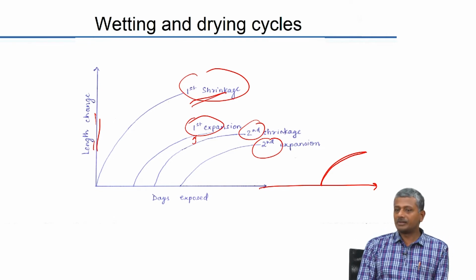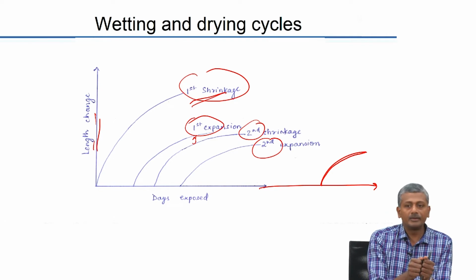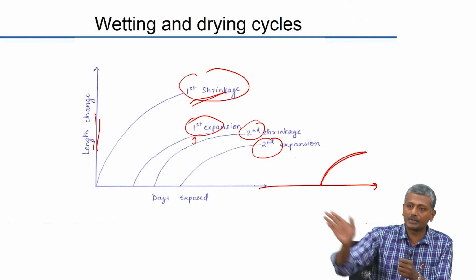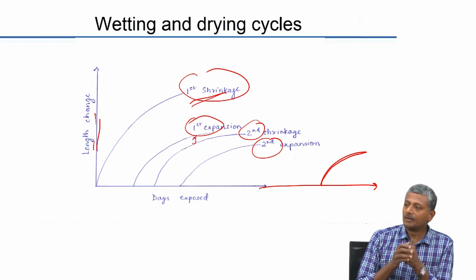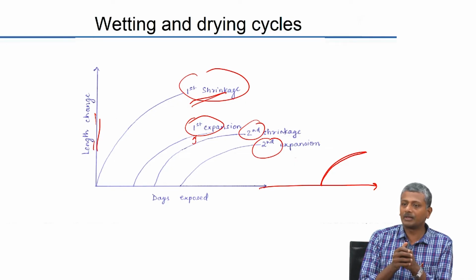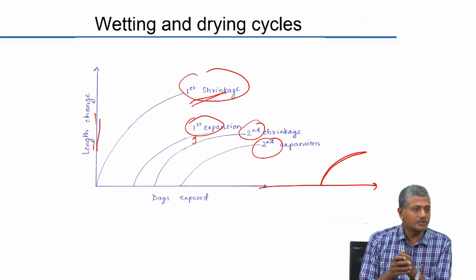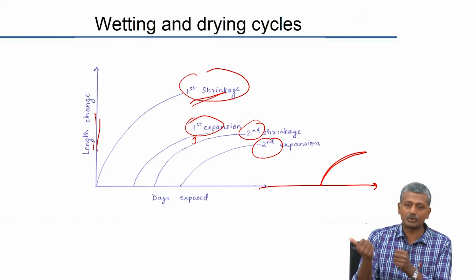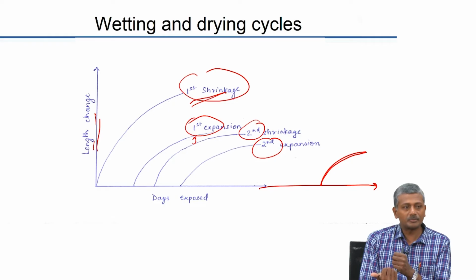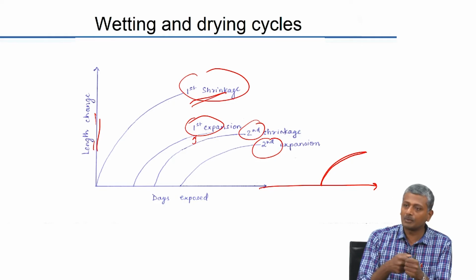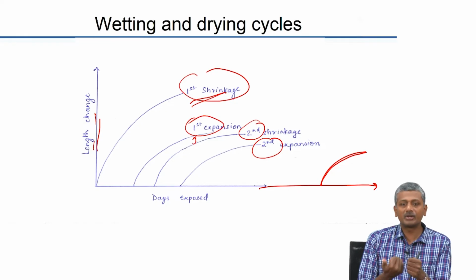The first shrinkage, as we discussed, alters the gel structure, which causes the water from the interlayer and adsorbed spaces to start getting removed, going towards the capillary pores, and the capillary pore water obviously goes out to the external environment. When the first drying happens, what type of water will first come out of the system? Water held within the fine capillary pores or coarse capillary pores? Obviously the coarse capillary pores, which is not held by very high capillary pressures, that will be the first to dry out. But that water drying out will not really cause much shrinkage, because it is going out of coarser pores. It is only when you start pulling out of the finer capillary pores that shrinkage increases.